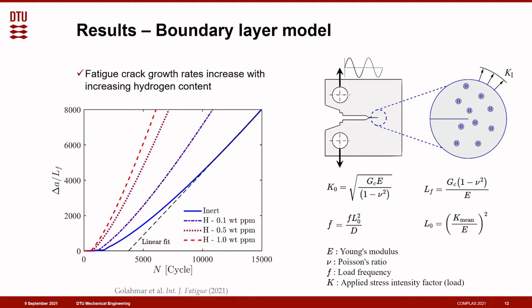The first case study is a well-known boundary layer formulation, which is used to gain insight into fatigue crack growth under small-scale yielding conditions. So what we have in the left figure is the crack extension as a function of the number of cycles and for different environments. The results shown here reveal that the model is able to capture the expected trends. For a given number of cycles, the higher the hydrogen concentration, the larger the crack extension.